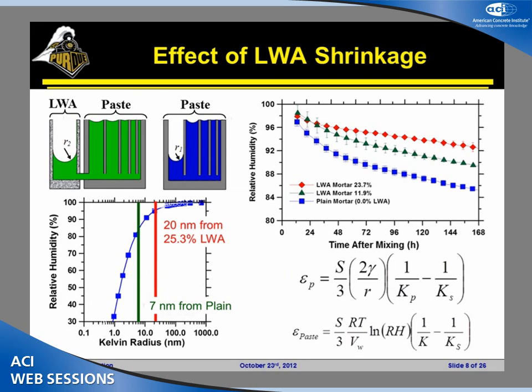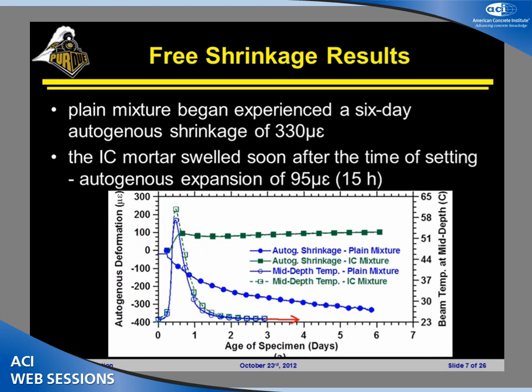We're keeping the pores inside of the paste full. And by keeping the pores inside of the paste full, we're not getting capillary stresses developed. Those capillary stresses are really what's responsible for the macroscopic shrinkage that we see. So we could actually say that the shrinkage of the paste is related to essentially how wet the concrete is, the degree of saturation, but it's also related to the size of the pores that are empty. So if we keep all the pores full, we keep the bigger pores full, we can substantially reduce the shrinkage, which is what we're seeing on this plot back here.